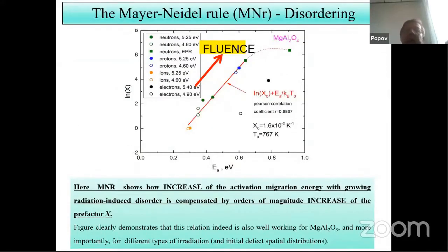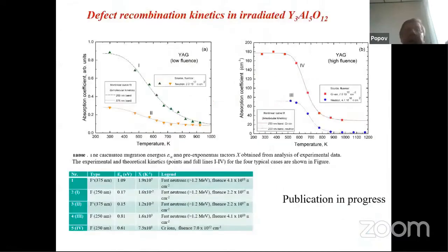But in the case, if you compare the situation with alumina and MgO, their fluence dependence goes the opposite way. And this is probably due to, in the case of complex oxides, the role of anti-site defects is so strong. They work as a stabilizer of the F-type defects or interstitials. And in this case, activation energy goes to a lot higher value than in MgO and alumina. And a similar value we obtained for classical scintillator yttrium aluminum garnet.